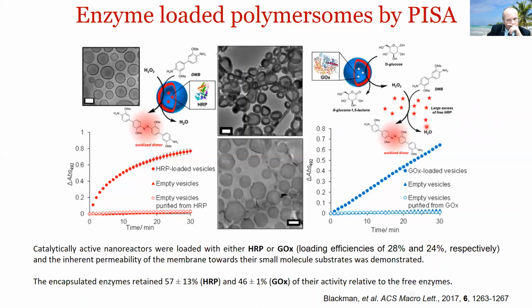And we demonstrated this for two enzymes, HRP and GOx. We looked at loading these, performing our conventional PISA polymerizations in the presence of these two enzymes. The size and properties of the polymersomes formed were very similar to that which was formed without the presence of the enzymes. We get loading efficiencies of, as you see, around 24-28% for the two enzymes, actually very reproducible. And we were able to show, for example with the HRP in this case, using standard colorimetric assays for these enzymes, quite readily that the enzymes were still very active and retained a good portion of their activity relative to the free enzymes. And so, as I said, this demonstrated the mildness of the polymerization conditions, but also the size selective permeability of the membrane.